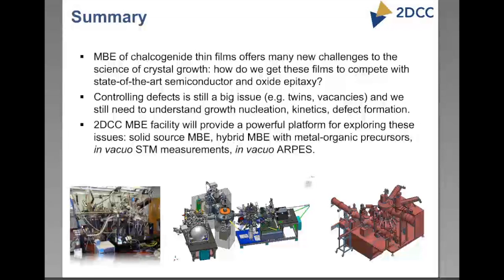But do we have a flange for that? Potentially, so potentially we might have the hydrogen plasma, but at least it's not in the immediate plan. The substrate temperature I think will go up to 1100 C. Okay, so in case you didn't hear, this is Anthony Ricciardella, who's the research scientist in charge of the MBE system. The substrate temperature will go up to 1100 centigrade.